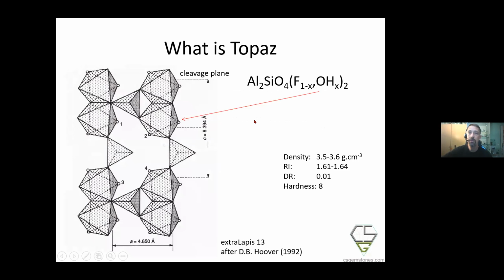Now, looking at the chemistry, we're talking about an alumosilicate. So we have 2 aluminums, we have 1 silicon, we have some oxygen, and we have fluorine and hydroxyl groups. And here the single difference in all the topazes is the content of fluorine that we have. It's not like tourmaline or garnet where you have lots and lots of different elements that play major roles. So topaz is a rather pure crystal with not high values of other elements that are incorporated in the crystal lattice.